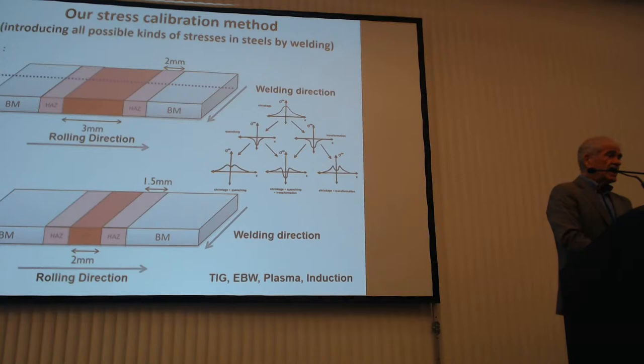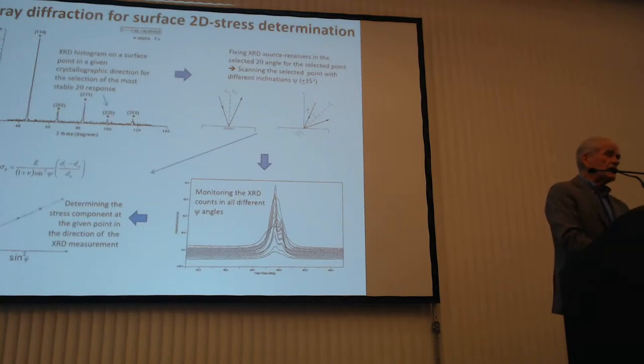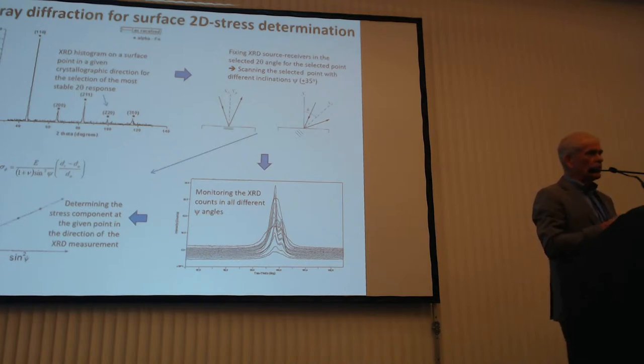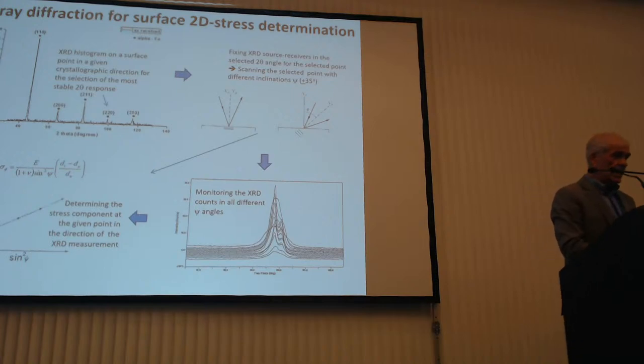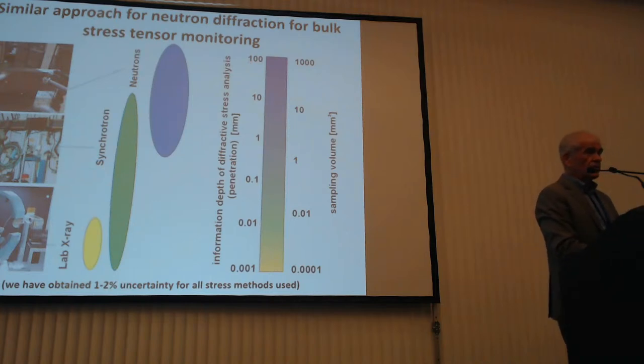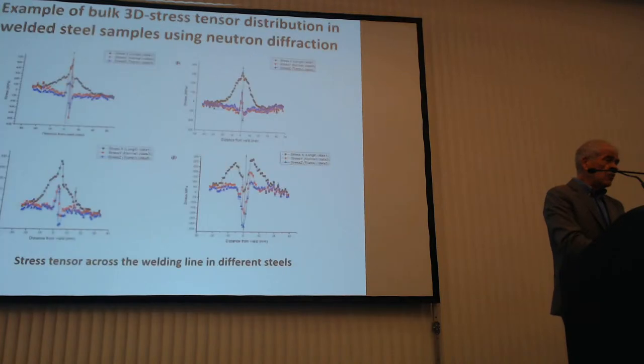Then we characterized the surface residual stresses and the bulk residual stresses by using the X-ray diffraction setup and neutron diffraction. I will not go into details on that, it's a technical matter, and we developed it over several trials in the beginning, and just in the last 10 years we were able to achieve monotonic and very small uncertainty measurements of residual stresses, either in the surface or in the bulk of the material. Then, the same thing we have done for neutron diffraction for bulk residual stress monitoring, and since we now know the stress distribution of these residual stresses in the steel, we used magnetic methods in order to monitor magnetic characteristics.